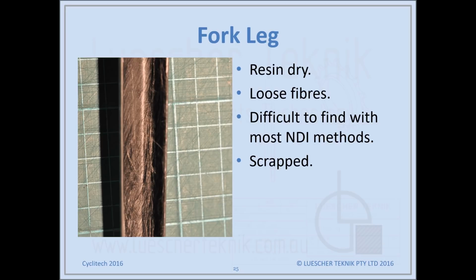This one's a little bit more unusual in that we found some resin dry fiber during the scan. What that means is basically the fibers aren't encapsulated in the resin, so there are loose fibers. You could basically pull these fibers out of the part. Now this is quite difficult to find with most methods. Like with an X-ray, there'll be very little density change. However, with an ultrasound scan, you'll find that the back surface will not reflect as much, and so you have a lower back wall signal, which you need to be pretty switched on to catch, but it's possible to do that, as was the case here, and then this one was therefore scrapped.